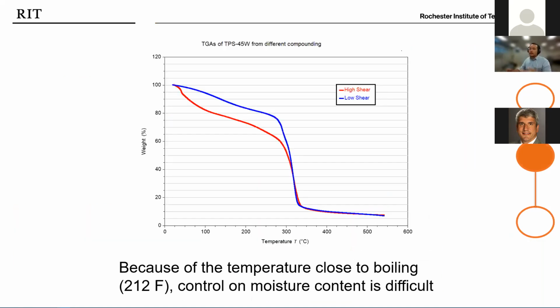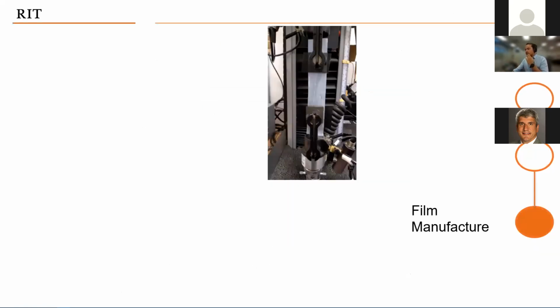But further testing, here you see a TGA of 2 different samples, showed us that we didn't have that 45% moisture. Why do we know that? Well, TGA gives us how the material behaves with temperature, right? Around 100 Celsius, we should see a drop because of the moisture content. And we see that we don't have a 45% drop. We have between 20 and 8, and the actual average of the samples was 12%. So even if we inputted 45% of water, the actual moisture content is around 12. And this loss of control is because even if I was careful and tried not to lose moisture, I lost it due to these temperatures that are very close to the boiling point.